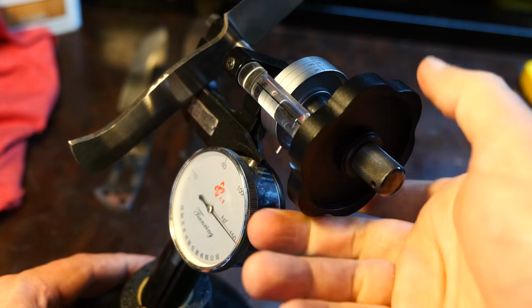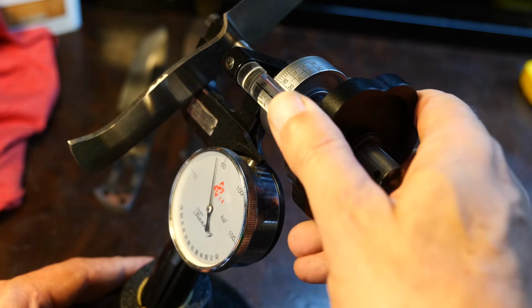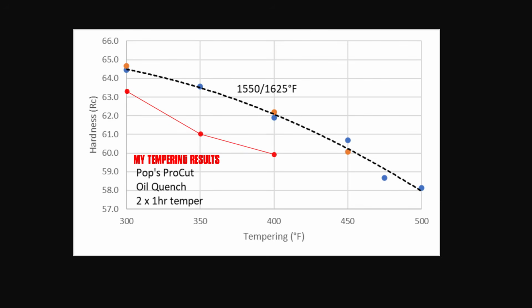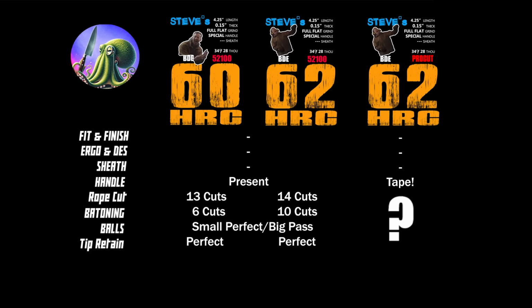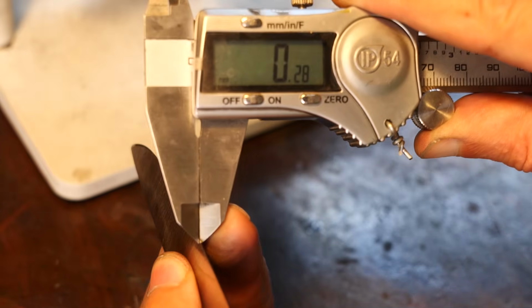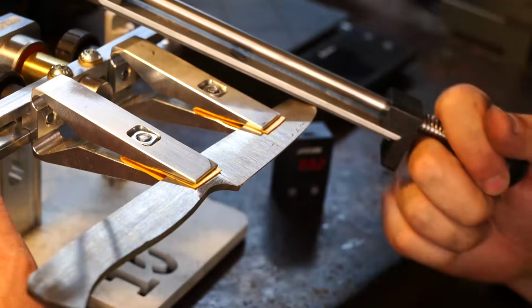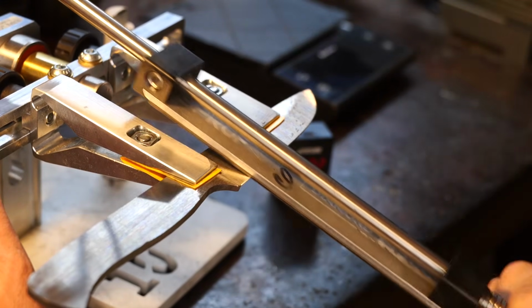It hardened to 65 HRC after quenching, but tempering was problematic as it constantly tempered about 2 HRC softer than it should have, according to Larrin's curve. Now, I ultimately brought it to 62 HRC for testing so that I can compare it to the results of a very similar 52100 blade I tested recently at that hardness. Both knives have nearly identical behind the edge thicknesses and are sharpened at 2000 grit at 17 degrees per side.